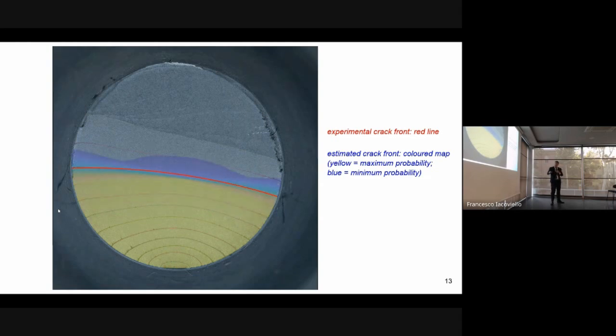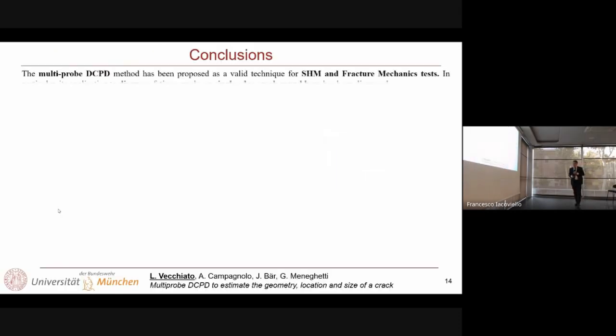You can see that the longer the crack, the better the estimation is, while for quite small cracks, for example, 0.1 millimeter, the initial notch, you can see that the algorithm is not so precise, so we can improve this method, but at least we can catch that a crack exists, first of all, obviously, and then that the crack is most probably located on the theta equal to 0 position. So somehow we have an idea that the crack exists, and we can do better using, for example, different techniques.